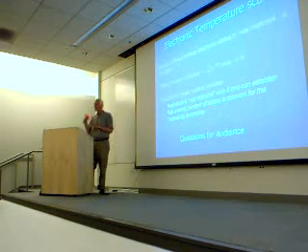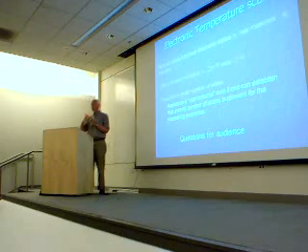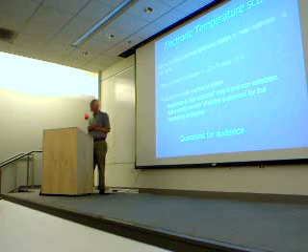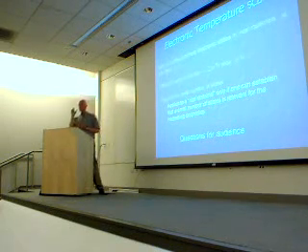And we know that lattice displacements are something we do a very good job on, and all these phonon frequencies and secondary minima. The ferroelectric transition itself at zero temperature is given quite nicely. So you can make a model of a small number of possibilities for each atom or each molecule, and then do statistical mechanics on that.